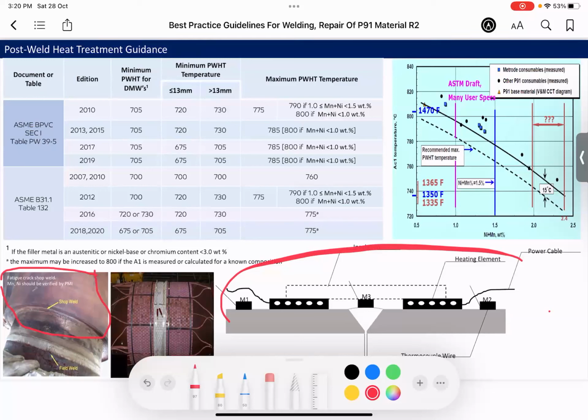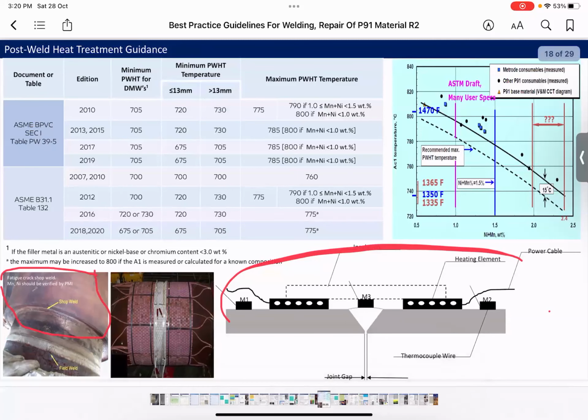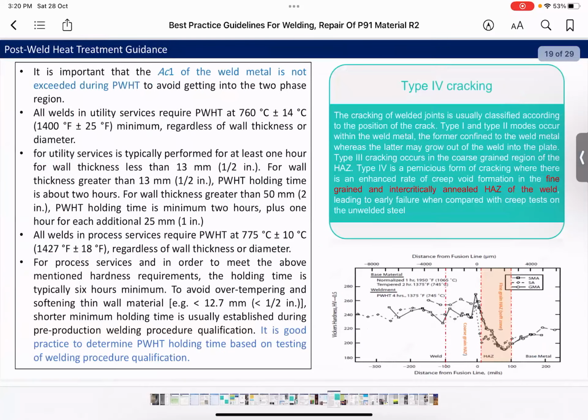This is the minimum and maximum PWHT temperature according to ASME Section I and ASME B31.1. For post-weld heat treatment, as I said before, the AC1 of the weld must not be exceeded. This is very important. Why? Because it will not have a martensitic structure, it will have a ferritic structure, a different structure in the steel that might be prone to cracking during service.